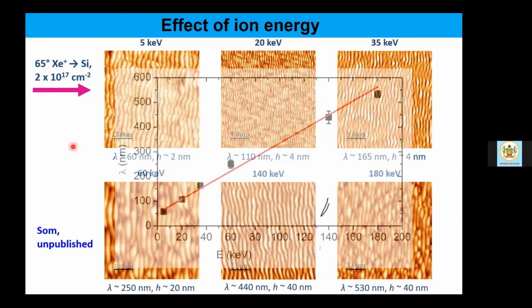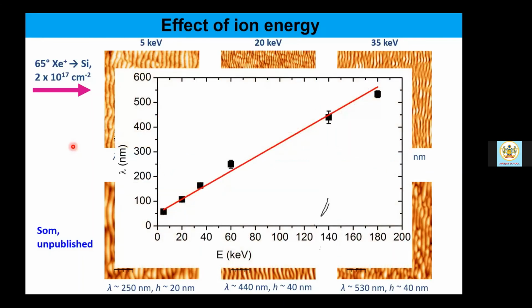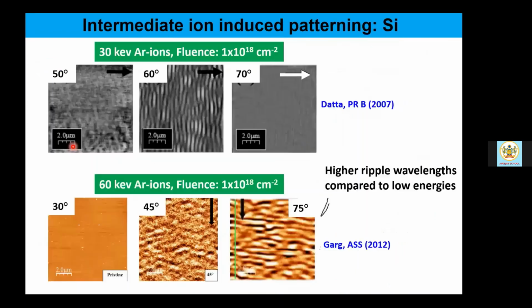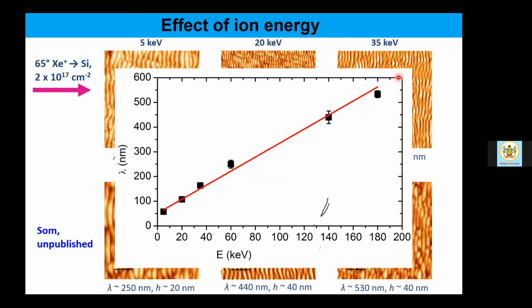And if we summarize the result for this particular work, we get to see that the wavelength linearly increases with increasing ion energy. It's a very important observation. And now, very quickly, I'll try to show, since we talked about this enhancement in ion energy here.